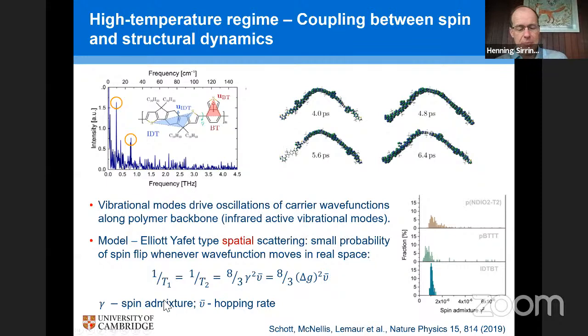So this parameter gamma that you see in this equation here, you can see here the results of a calculation of this spin admixture depending on the conformation that these molecules have in the solid. You get a distribution of spin admixtures and a distribution of spin orbit coupling. So the spin orbit coupling is quite sensitive, for example, to the molecular orientation, molecular torsion. So it's not just dependent on the chemical composition.